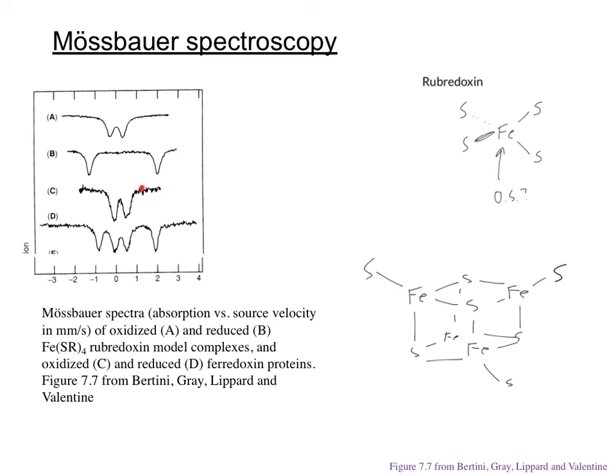And so in the oxidized rubredoxin protein, we see a match to the model complex. And in the reduced rubredoxin, we see equal intensity of the larger isomer shift and smaller isomer shift species. So it suggests it's an iron 2 to iron 3 complex.